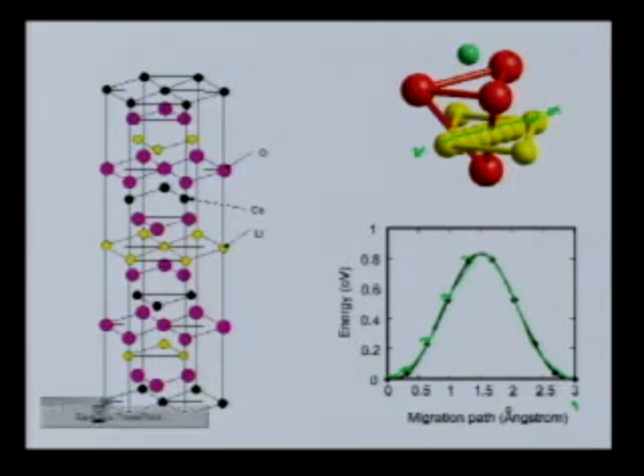It's very nice how you get these activation curves. But the problem is there are two paths in this material, so you're starting to run into a particular problem of kinetic Monte Carlo: let's say you thought that was the path, well, you'd be very wrong, because there's another path. That's one where the atom, rather than going straight through this bond, takes a curve into this tetrahedron and comes back out.